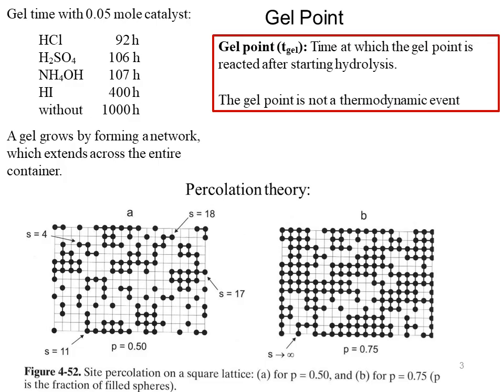Gel point. Gel point is represented as T gel, the time at which the gel point is reached after starting hydrolysis. The gel point is not a thermodynamic event. Gel time with 0.05 mole catalyst for different acids and bases is given below. For HCl 92 hours, for H2SO4 106 hours, for NH4OH 107 hours, for HI 400 hours.